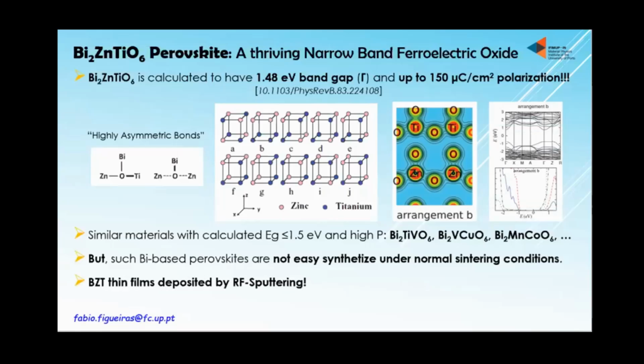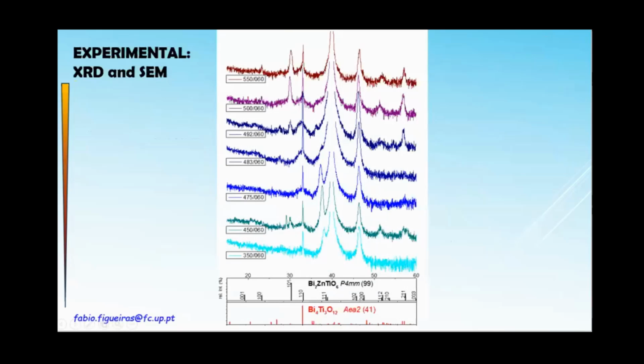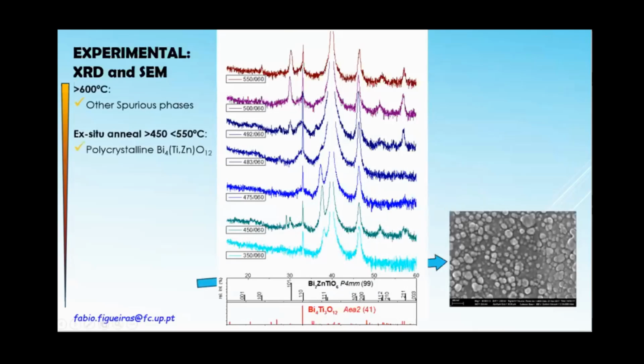What's the catch? The bismuth perovskites are not easily stabilized at room pressure and room temperature. So sintering these materials, putting bismuth oxide, zinc and titanium together, will probably get you another material that is not a single-phase perovskite. So we go for RF sputtering, inducing the phase in a film, and the high strain of the film should stabilize this material. So there was a very long practical and experimental research for a theoretical material. And our results demonstrate that we try to produce the material at very high temperature or from very low temperature.